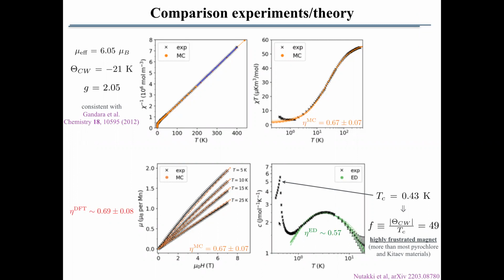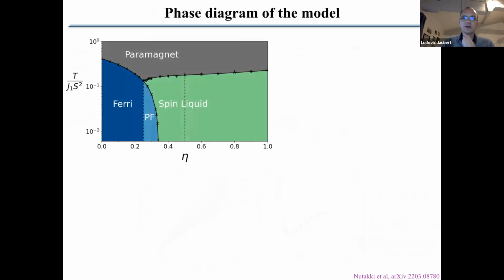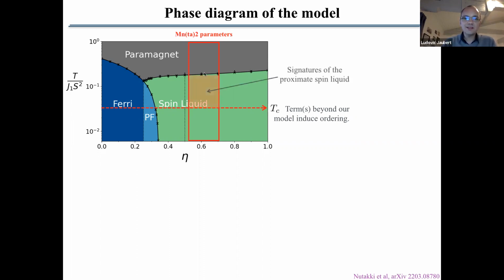And so what it means is that we have a parameterization of manganese parameters in this region of the phase diagram. We have a phase transition at Tc, which is not in our model, because in this region of the phase diagram, when you do classical Monte Carlo simulations, we do not find any phase transition. So this phase transition at Tc is beyond our model, and we need to introduce other terms to understand it. But our point is that at this intermediate temperature above Tc, we expect a regime of temperature where we can see the proximity of this spin liquid system.